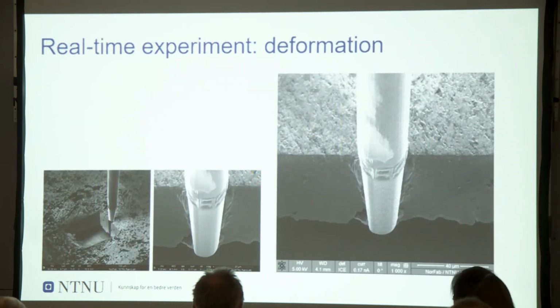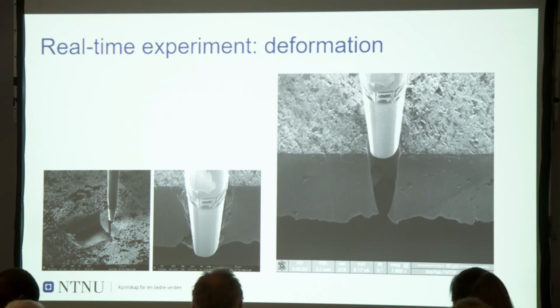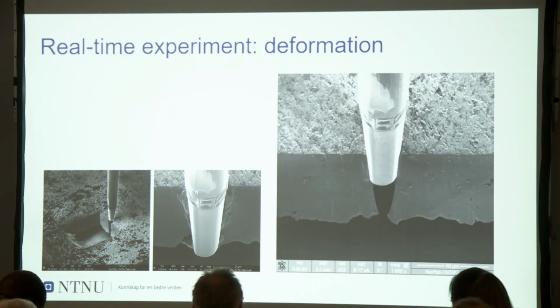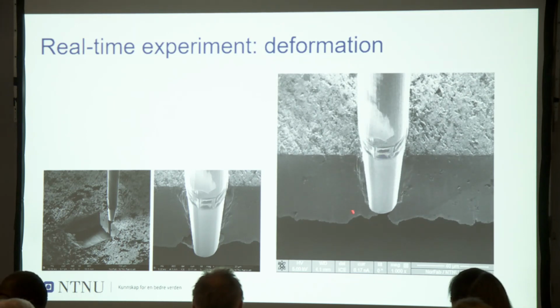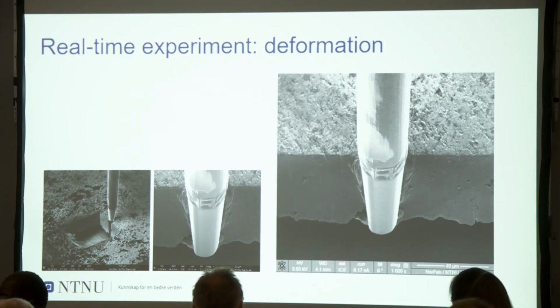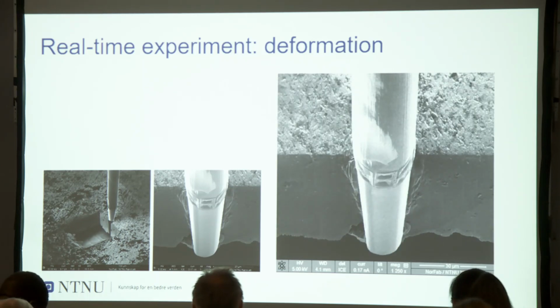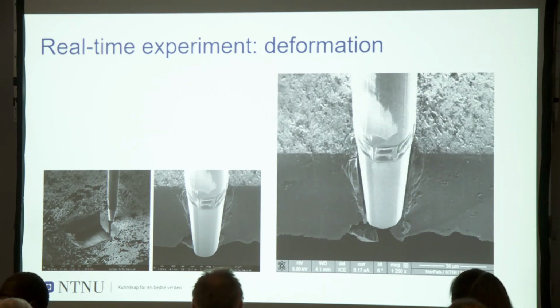This is another experiment, a real-time experiment, where we would like to see the effect of this plastic deformation on the edge of the hole. So we make a kind of half of the hole, with the visible part, and we apply the same load to see the severe plastic deformation occurring at the edge here. Of course, in this case, the bonding did not occur because the hoop stress was completely missing.